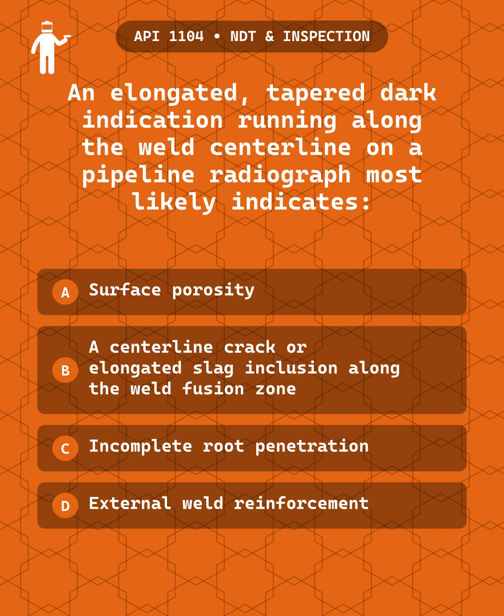Question 8. An elongated, tapered dark indication running along the weld center line on a pipeline radiograph most likely indicates A. Surface porosity, B. A centerline crack or elongated slag inclusion along the weld fusion zone, C. Incomplete root penetration, or D. External weld reinforcement.